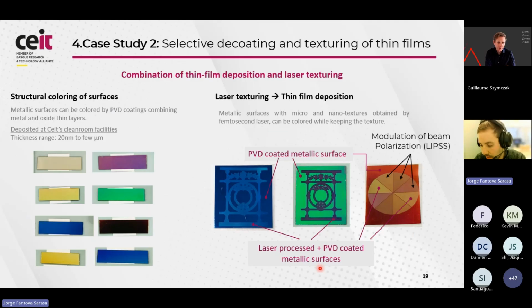And lastly, linking with what Iago mentioned, it is very interesting to combine both the capabilities of thin film deposition and also laser decoating or texturing. In CEIT, we can generate metal and oxide coatings with thicknesses from 20 nanometers to a few micrometers, which can provide not only this very beautiful coloring that you see here, but also tune appropriately the optical properties of the surface of the substrate. And furthermore, by combining these two, you can, for example, laser texture the substrate before the coating to provide some functionalization, like for example, to control wettability or to have some anti-counterfeiting features.